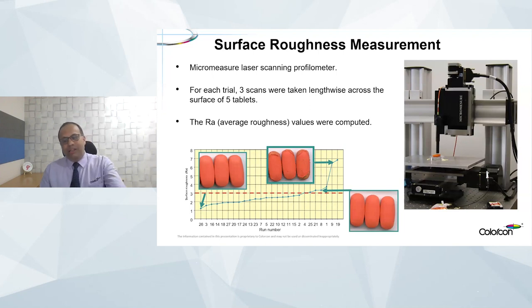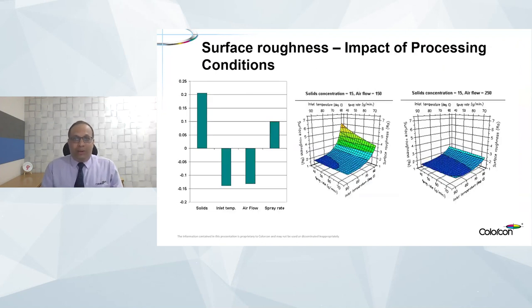So in cases where we are really looking at achieving smoother tablets, there could be this type of quantitative measurement. And of course, how do the parameters that we discussed impact it? Of course, the temperature and airflow are impactful factors here. So they are reverse impactors. From the graph, you can see an increase in temperature and an increase in airflow would decrease the surface roughness. That is, you see both the bars coming on the reverse side. So if you are looking at increasing roughness, then you would have to decrease temperature and decrease airflow. Our objective is to increase smoothness, and that is why you need to have a higher temperature and higher airflow. And you could see that the solids content and spray rate are on the reverse side.